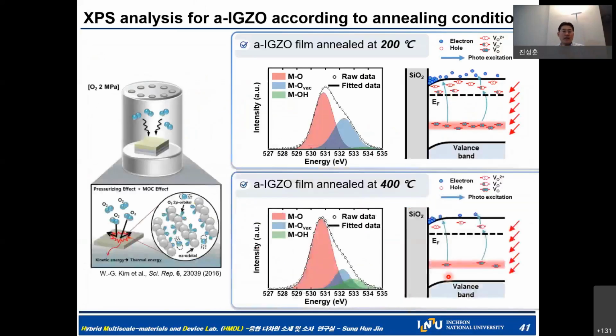So now let's move on to the analysis for indium gallium zinc oxide according to the annealing temperature. As you can see here, when adopting just 200 degrees Celsius, there are so many defect states generated inside. Because of that, severe photoresponsivity is achieved. However, when you utilize 400 degrees Celsius, the oxygen vacancy is dramatically reduced. Because of that, the n-type property is guaranteed. However, photosensitivity is dramatically reduced.